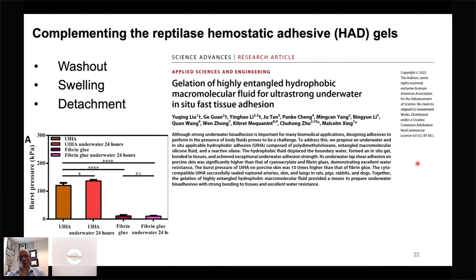Now, one of the issues that we had was with the hemostatic adhesive gel that we developed. First of all, it's cross-linked by visible light. I forgot to mention that. That was one of the benefits as opposed to UV light, because UV lights are not always safe. One would imagine squeezing this gel, which is a liquid-like material, and then you shine a visible light, and that gets activated because of eosin Y, and then the cross-linking process starts, and that's basically how it stops the bleeding by forming a gel.